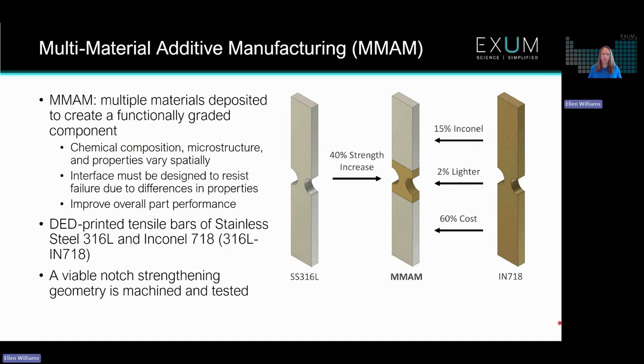They went through a pretty rigorous design process of creating these notch-strengthened tensile bars that used stainless steel 316L in the grips and then strengthened the notch with an Inconel 718. If you're not familiar with that term, that's a nickel superalloy and has some really good mechanical properties, but it is more costly and heavier than something like a stainless steel. So you can see how it's used only in the notch where that part needs to be strong.